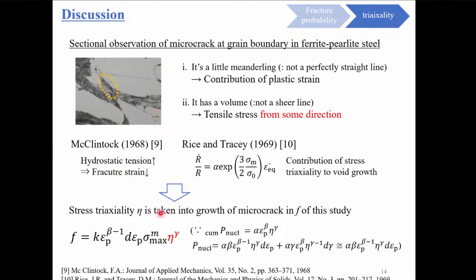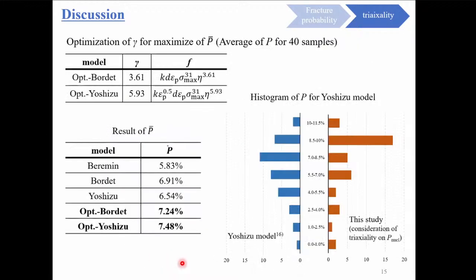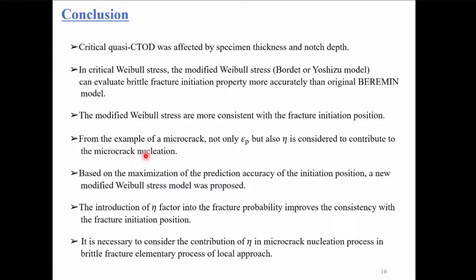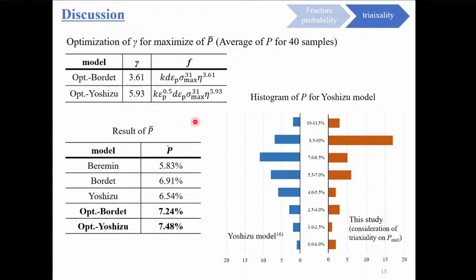From this fact, it was thought that the tensile stress from various directions, that is stress triaxiality, might be involved in microcrack nucleation. Some previous studies have mentioned that an increase in triaxiality can promote brittle fracture and its elementary process, void growth. Therefore, we introduced the factor of triaxiality into the fracture probability and optimized gamma so that the fracture probability becomes maximum likelihood, and the increase in the fracture probability was confirmed. Although the introduction of the factor of triaxiality in this study was quite simple and the exponent was determined from the calculation results, at least the possibility that triaxiality is involved in microcrack generation was suggested.